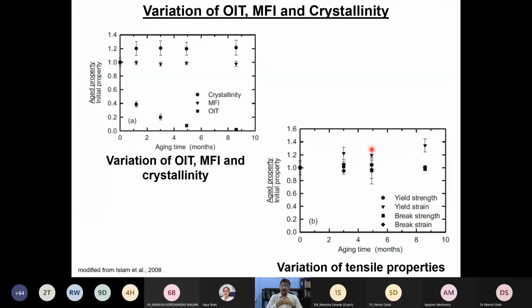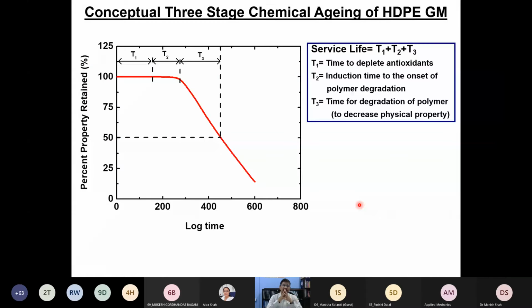Not only the OIT, the melt flow index, as I told you, molecular weight and crystallinity also we measured, and then we also measured the yield strength and break strength, and all these things were measured. And by taking all these things, we can back calculate the service life. How do you back calculate? In order to calculate the service life, we use the 3-stage conceptual model proposed by Grace Hsuan of Drexel University. And what she proposed was a very simple concept.